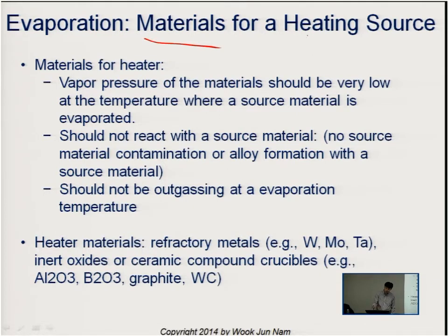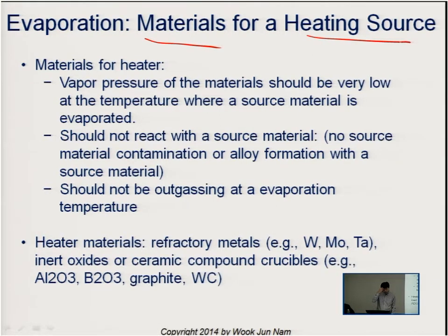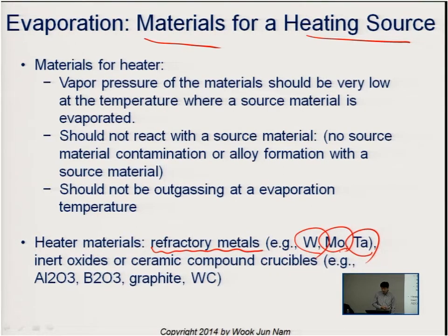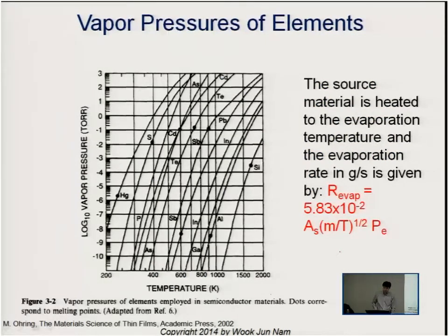The materials for the boat, the heater materials, are basically made out of refractory material which has a very high melting point. At high temperature, ideally that material does not form any compound with your source material. So that's the requirement for the heating source material.